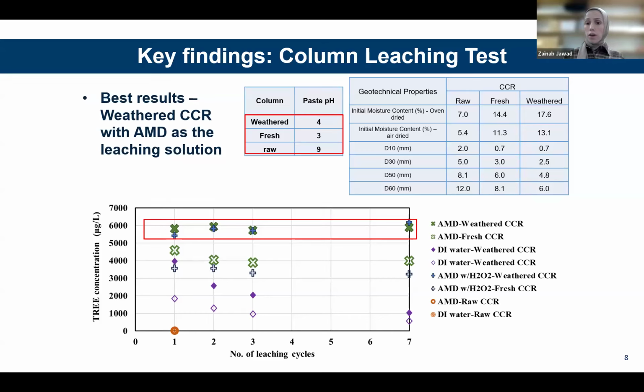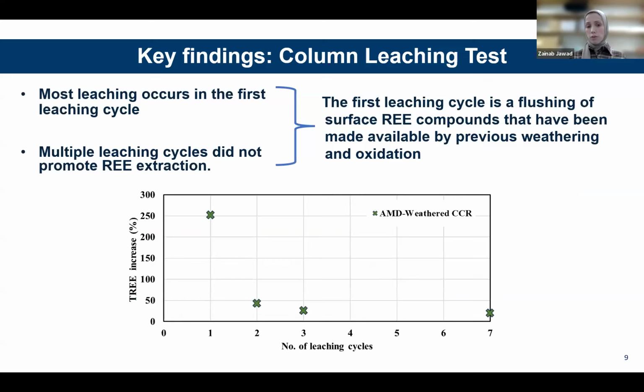The second reason was the high moisture content within the weathered refuse, and we know that water is very important for oxidation. The third reason is the small particle size range of the weathered refuse, and that's again due to weathering. As the particle size decreases, the surface area available for oxidation becomes bigger. So I'll continue my results with the column that gave us the best results, which is the one filled with weathered refuse and AMD as the leaching solution.